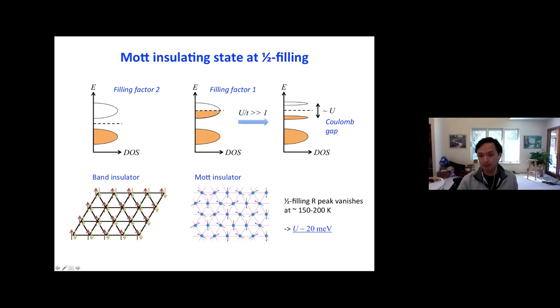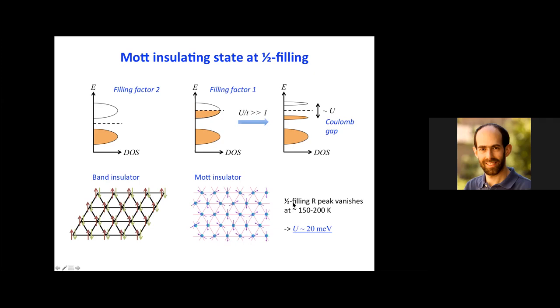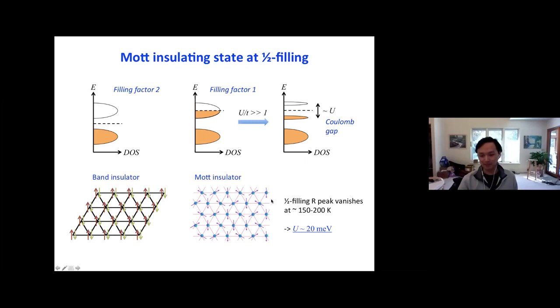And so by just looking at the temperature dependence, yeah, is there a question? Oh, okay, right. By looking at the temperature dependence of the filling factor one resistance peak, it vanishes at about 150 to 200 K. So we can basically make a lower bound estimate of U of about 20 meV for this Hubbard gap here. And I call it a lower estimate because for an interacting system, such a gap is also temperature dependent. So it's just a really rough estimate. And recently we have done some compressibility measurements, and the measured gap is actually bigger than this, about 60 meV.